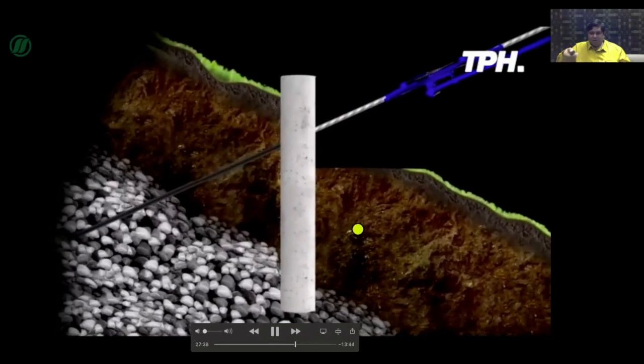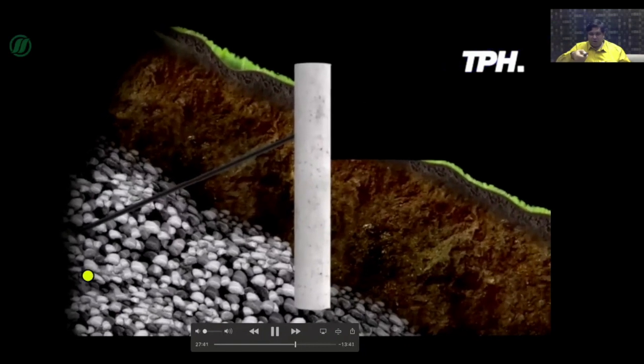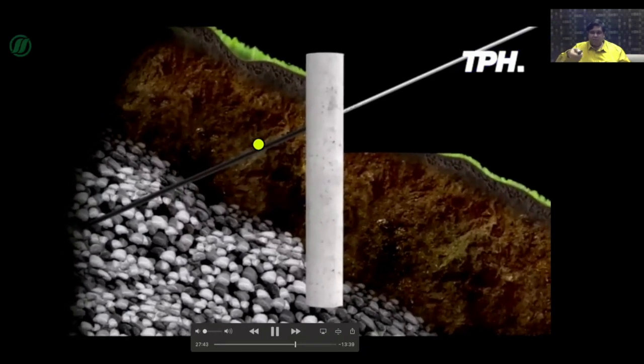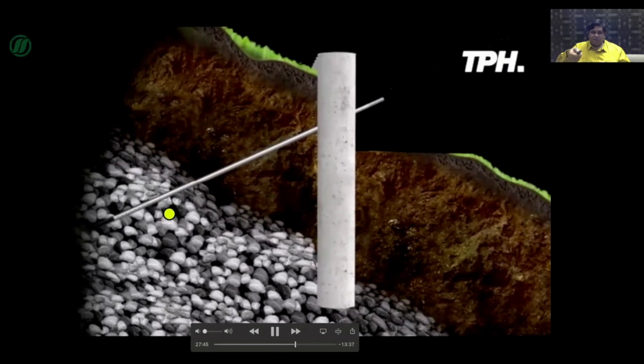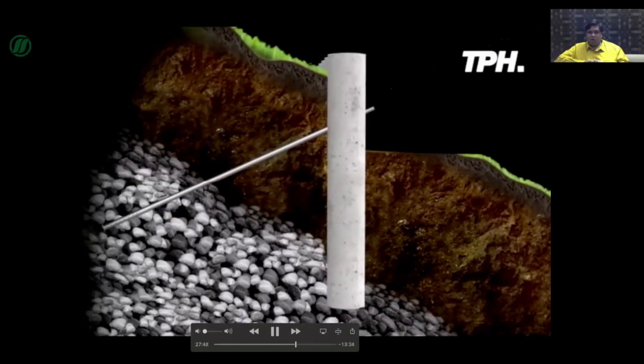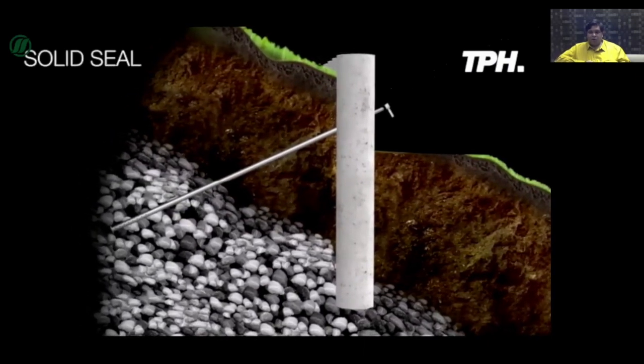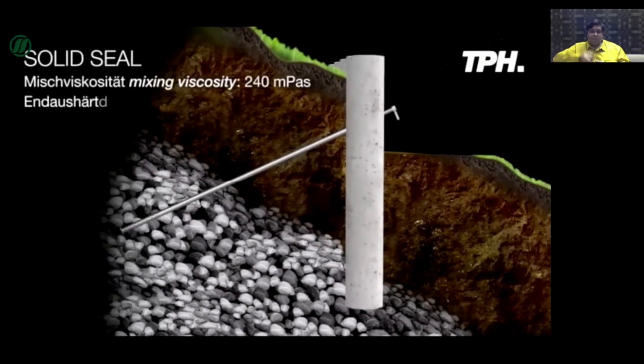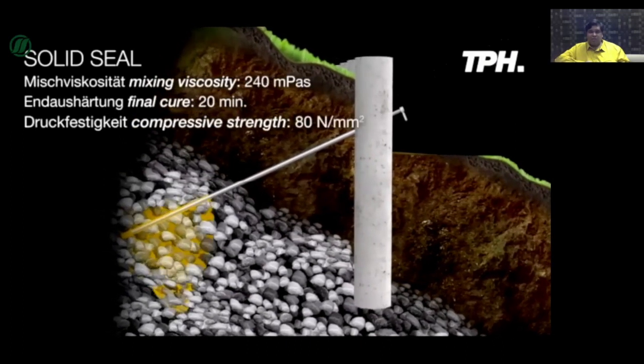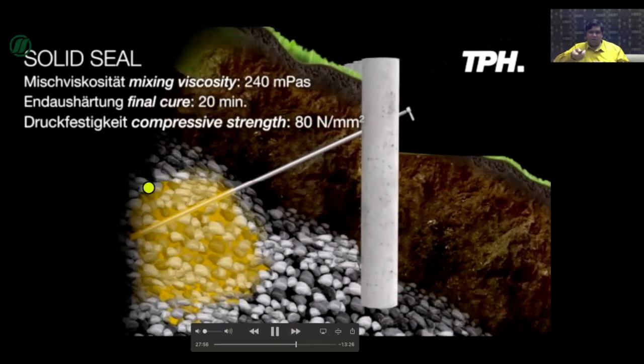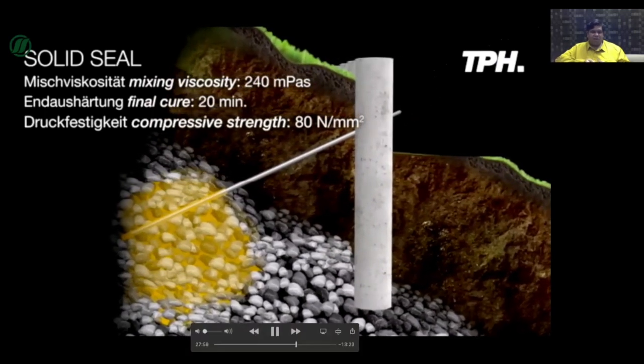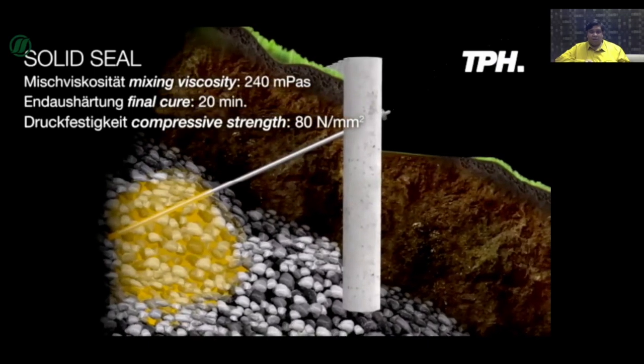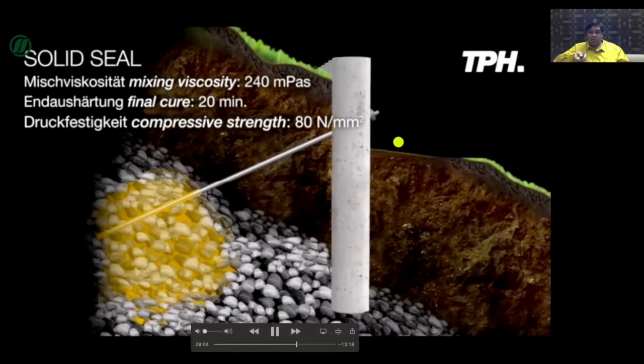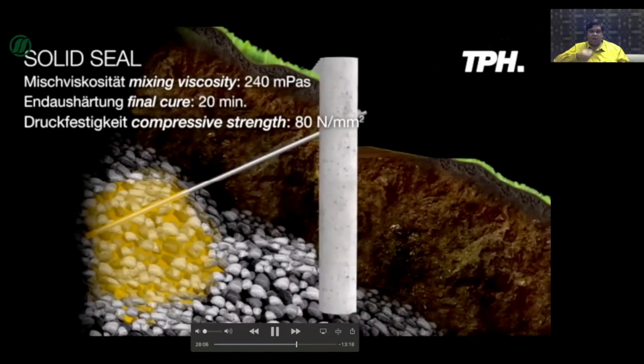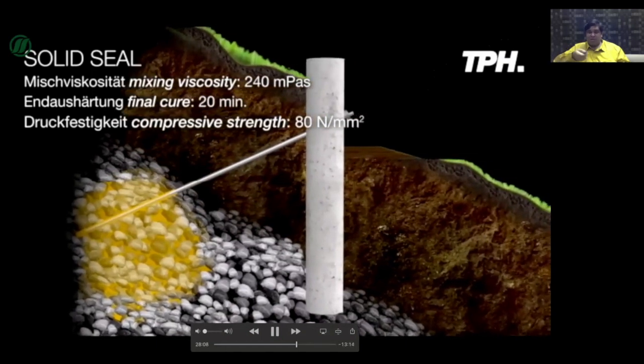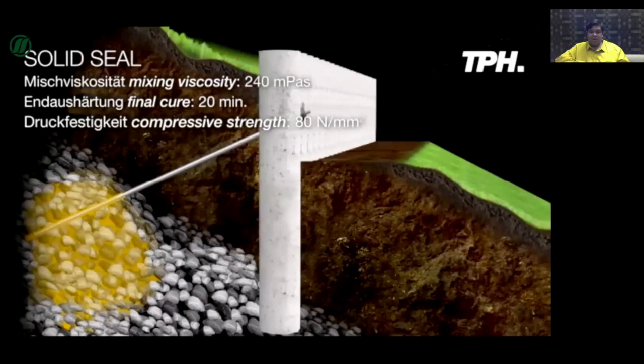So we are using drilling methods to go right into the fractured area. Use the right kind of injection spiles or even long tubes, the injection lances, and then a material like Solid Seal, for example. It again has a very low viscosity, maybe hardly 240 mPas. It has a very high compressive strength, reaching almost 80 Newton per mm square. And one of the main things is that it cures very fast, hardly 20 minutes curing time.